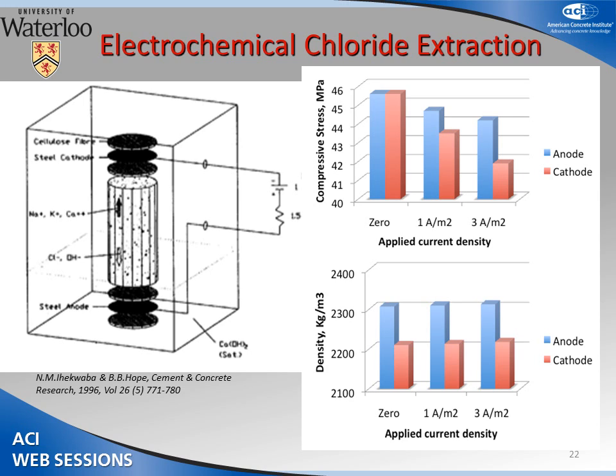In this case, there's a cylinder of concrete which is partially immersed in a solution. This is the cathode, and this is the anode, and a current is applied between them. And after a certain period of time, this part and this part were tested for both density and for compressive stress. And as far as the density is concerned, you can see that the cylinders were cast upright, and so there must have been some bleeding here, because to start with, with no current applied, there was a difference in the density of the anode and cathode area, the cathode being less dense.